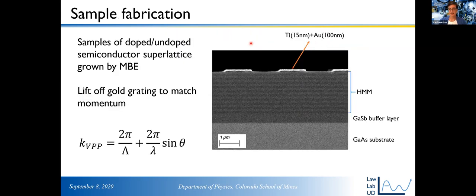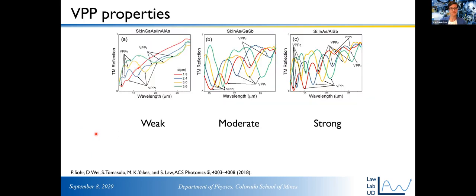So what we did is we grew a bunch of metamaterials, we fabricated these grating couplers, and then if you change the period of the grating coupler, you change the wave vector of light. So by changing the period of the grating coupler, we can actually map out the dispersion of these modes. And that's exactly what we did. I'm just going to skip to the one that works the best, which is this material pair, indium arsenide and aluminum antimonide. If we just look at this one here, this is the first order VPP mode. You can see it's a dip in reflection. And you can see as we change the period of the grating, which is in this legend here, we can watch this mode move. We can actually map its dispersion.